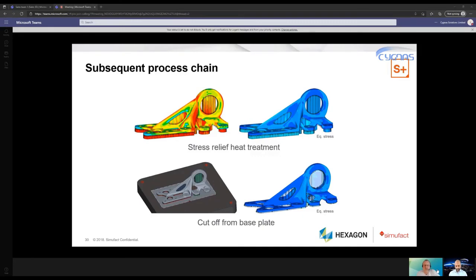When you look at the subsequent process chain, some examples here. For example, stress relief heat treatment: of course, you have a significant stress reduction, but a lot of times you still have some stresses. And when you cut off the plate on the bottom part, you have an additional stress reduction, which is linked, of course, to an additional deformation. And you need to know that before you print. And you can also compensate for that, so that after removing the part from the plate, it is straight and within your tolerance. It is a really very nice application.